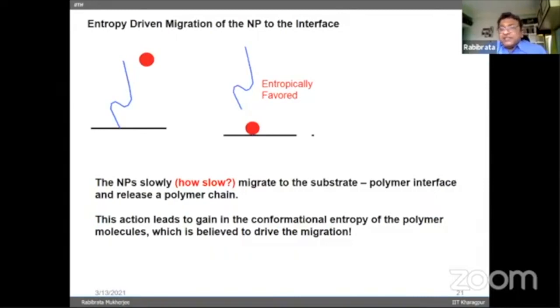Why? Because of a polymer chain that is attached to the free surface or at the substrate surface of the film. So this is the substrate, and here you have the film. A polymer chain that is attached to the substrate actually has reduced conformational entropy, because the polymer chain cannot oscillate in all directions, as you have a rigid substrate on one side. So if a particle now migrates to the substrate, fills up a spot and releases one polymer chain, which migrates back to the bulk, then the polymer chain gains conformational entropy. So there is always a competition and balance between the enthalpic effect and the entropic effect. And the physics is absolutely fascinating.